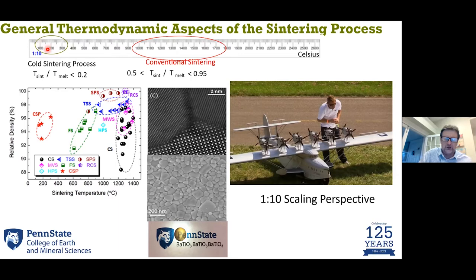In fact, the rule of thumb in a textbook is the sintering temperature over the melting temperature lies between 0.5 to 0.95. Cold sintering is below 0.2, often 0.1. So in the case of barium titanate, this is cold sintered barium titanate. You can see here beautiful triple points between three adjacent grains, a dense microstructure,